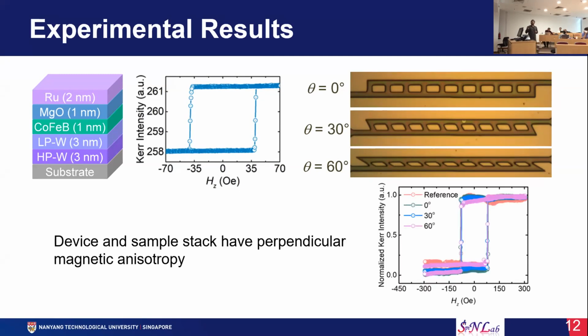Now we did the same Kerr microscopy setup. We did the same hysteresis loop plot, and we get this perpendicular magnetic anisotropy. The only difference is that the coercivity gets double compared to the thin film stack, because of the low pinning, low nucleation sites present in these devices.